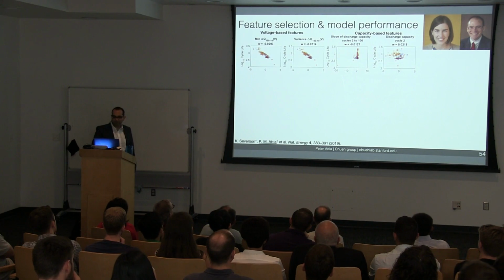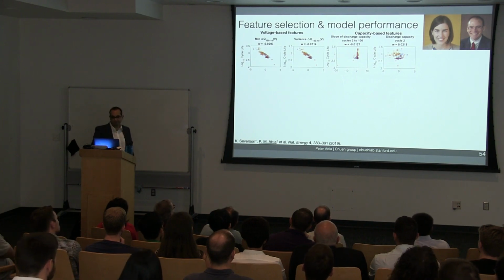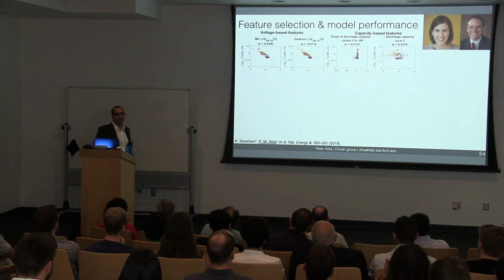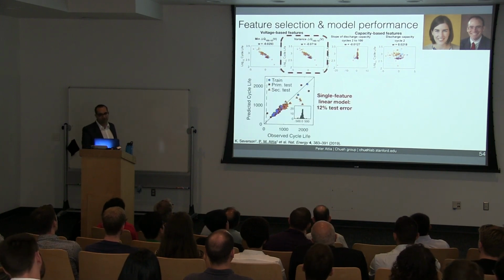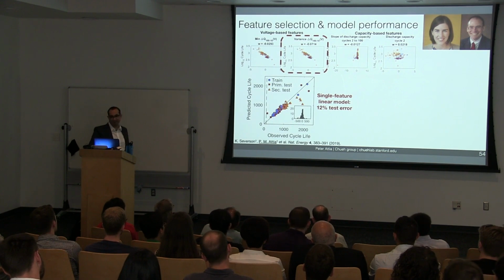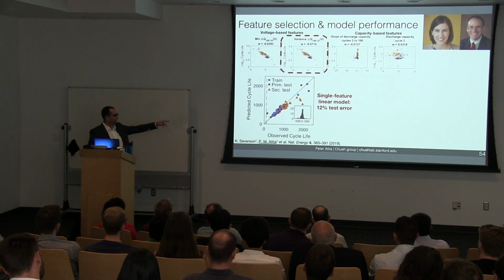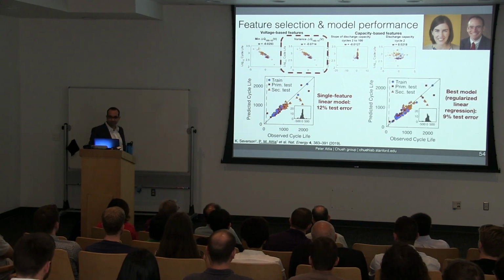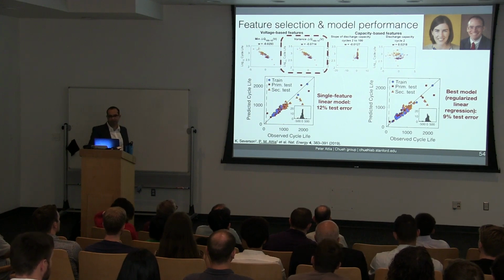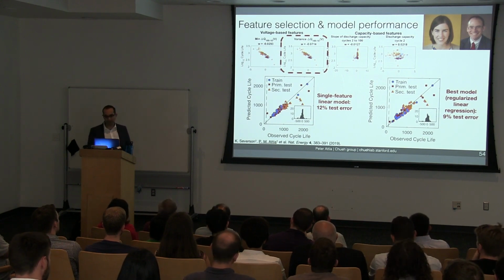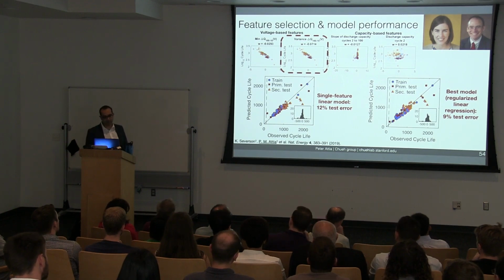So now we're ready for machine learning. The machine learning part of this work was led by Kristen, Richard, and my team. We created 20 features based on data streams like voltage, capacity, temperature, and terminal resistance. And I've shown just 4 of these features here. Now it turns out if we build a linear model with just that single feature from the previous slide, we get something like 12% test error. Again, we're just using data from the first 100 cycles, just to the left of the dotted line here. If we compare that to our best model, we get around 9% test error. This model chose the best 9 features out of a total pool of 20. So additional data streams like capacity and temperature do seem to improve the predictions, but the primary predictive performance comes from the voltage features.